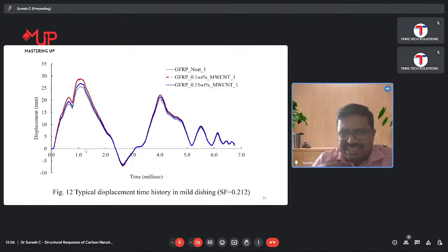Again, since it is a short duration, due to the elastic properties, the material will come back to its original position. Since it is coming at higher velocity, it goes to the negative deformation. And again, when the second shock wave comes, it pushes the plate again. But the second shock wave will always have a much lesser intensity compared to the primary shock wave. So the deformation caused by the second shock wave will be much lesser.